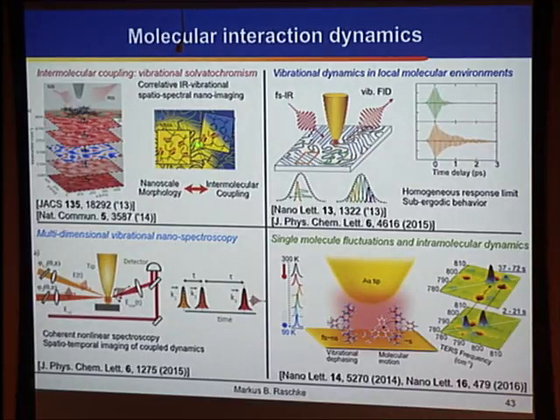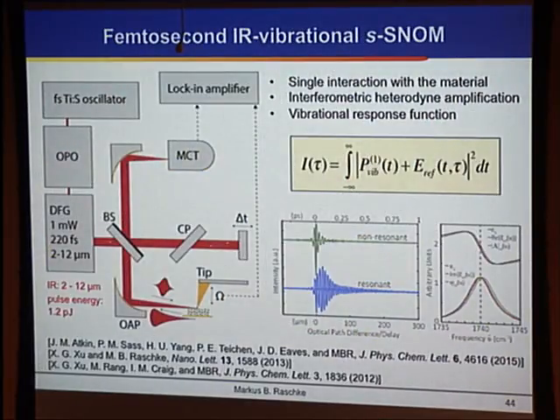And so what I'll show you is that this intermolecular coupling, in fact, determines the nanoscale morphology in molecular heterogeneous systems. But it is then again this intermolecular coupling, controlled by the nanoscale morphology, which determines how efficient, say, charge separation or other processes are in these phase-separated multi-component molecular systems. And so I'll focus on this example. We do related work even on the intramolecular scale, looking at intramolecular relaxation of vibrational motion. But I think this is a good representation, and I noticed that many of you work in soft matter-related systems.